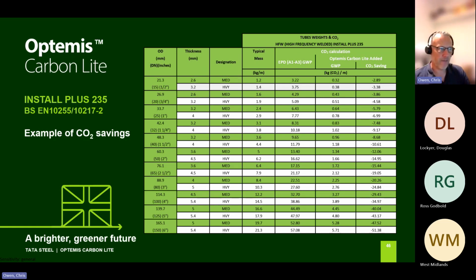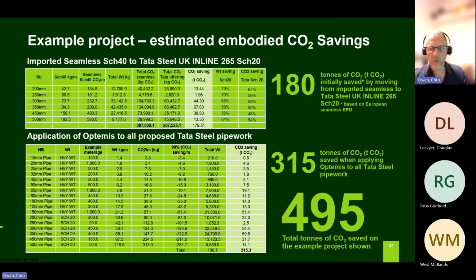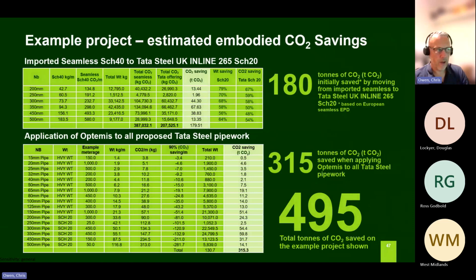And when I gave the first CPD, we had a rough example, but since we did this, we've now had a project in London, which is taking the Optemis tube. So we worked with the specifiers and the consultants, and we were able to convert the initial large diameter pipework from imported schedule 40 seamless to UK welded schedule 20. The higher grade of steel meant that we can satisfy the service life and the pressure integrity. So that technical conversion saved 180 tons of CO2.